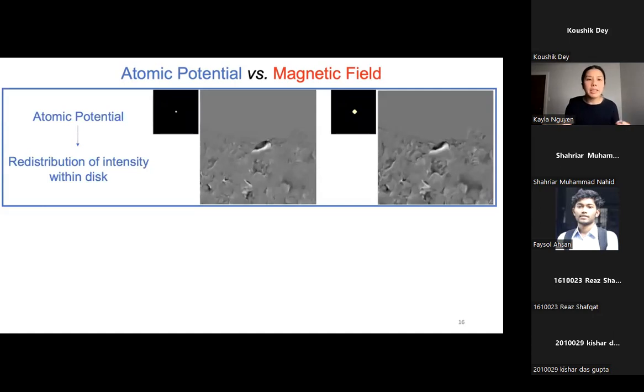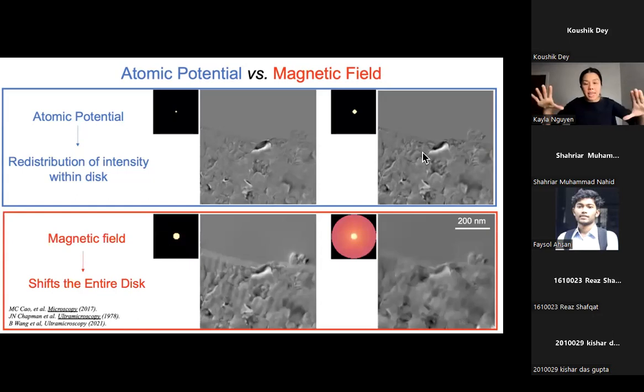If we take only information from inside of the bright field disk, we get a redistribution of intensity within the disk that gives us back our grain structure. However, if we take our entire diffraction pattern, we know that in the electron microscope, the electron beam gets deflected by the local magnetic field. What it does in diffraction space is shift the whole disk. From that, these lines here represent the ground state of a skyrmion, these helical phases. For skyrmion structures, you have to turn on a magnetic field for it to actually curl to form skyrmions from the Dzyaloshinskii-Moriya interactions. So within the ground state, what we see are these helical phases that we can extract from our magnetic imaging.